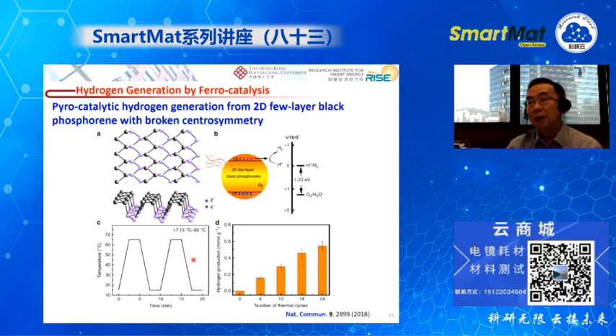Then we further extend this kind of catalysis to 2D few-layer black phosphorus. And we know for black phosphorus, we do not have any polarization because of the central symmetry. But for the few-layer one, the central symmetry is broken. So the few-layer black phosphorus shows some pyroelectric property, and then we make use of this pyroelectric few-layer black phosphorus for pyrocatalytic hydrogen generation, and we cycle the material in different temperatures, and we found the hydrogen release.